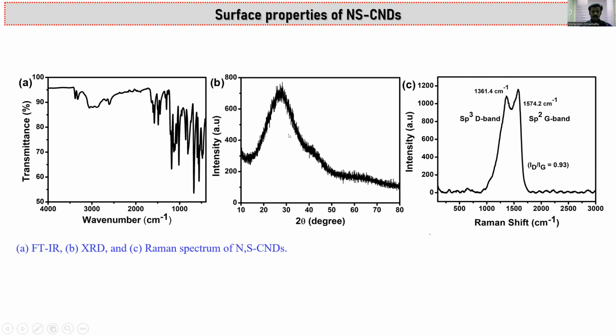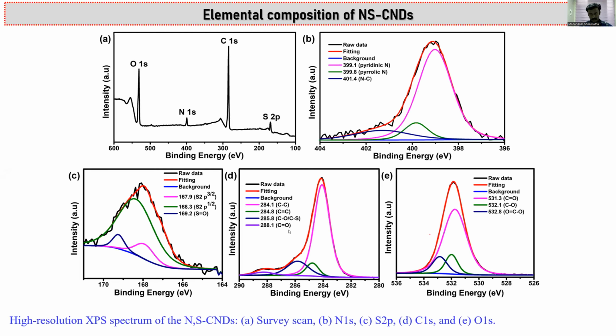Another one is the Raman spectral analysis. We get two different peaks: the first at 1,574 and another at 1,360, assigned to the two different bands, D and G bands. The intensity ratio is calculated as 0.93, so we can confirm the graphitic structure. In the surface analysis there is no variation between the previous section and this section. We also get the same sulfur double bond O, carbon double bond O, and carbon binding with the sulfur atoms.